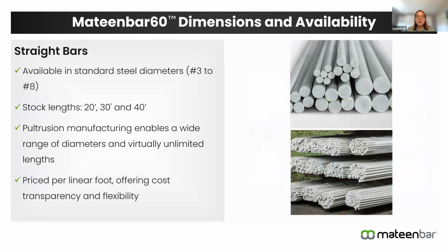So if we think about availability, Mateenbar60 is available in standard steel diameter sizes. So it's specified the same, number 3 to number 8 in our particular case. The ASTM goes up to number 10. And there's actually discussions to increase that to a number 11, but that's not in the specification yet. Our stock lengths are 20, 30, and 40 feet, though we're working on technology to get out to 60 feet, and then theoretically it could be as long as you want, given the manufacturing process. Really, the limitations are logistics and transportation.